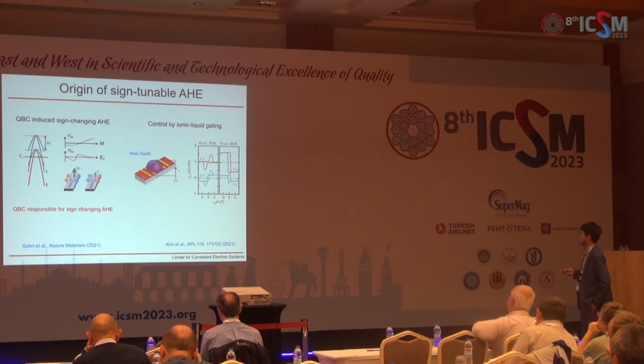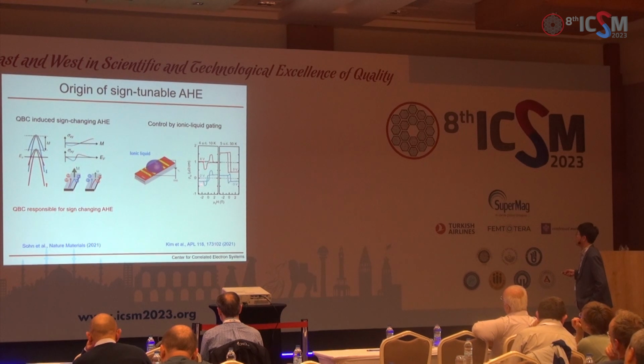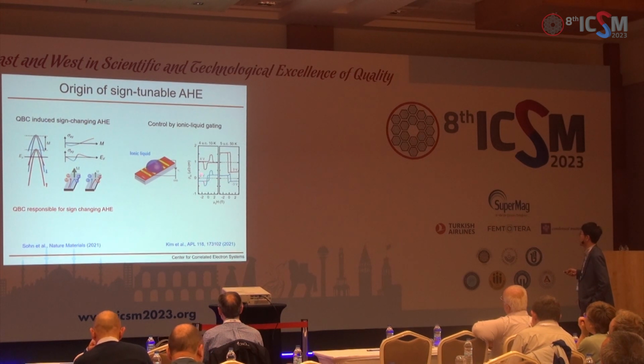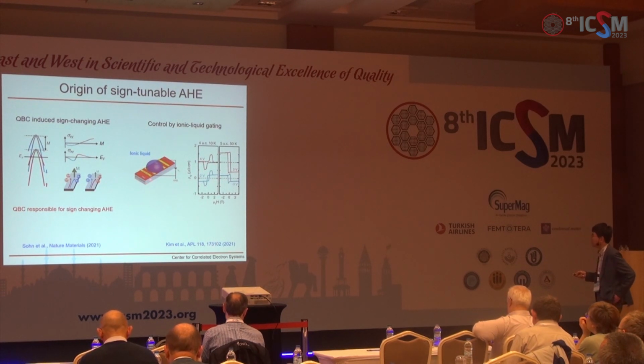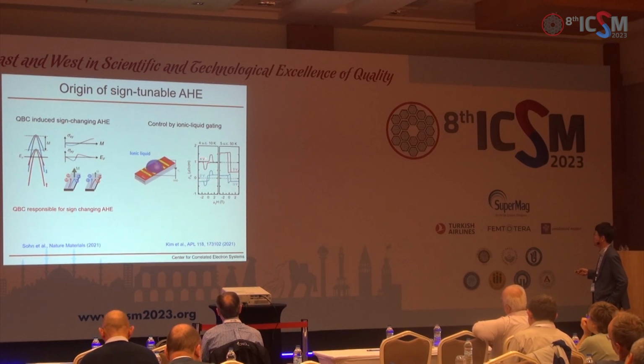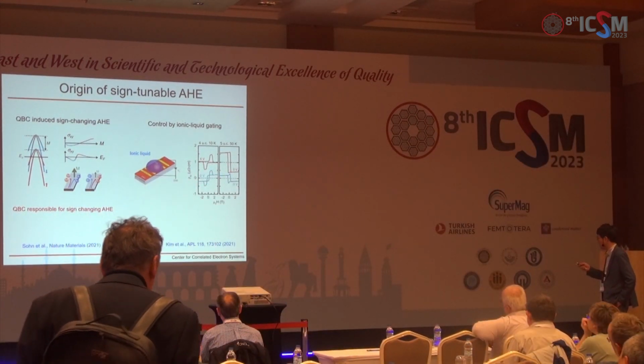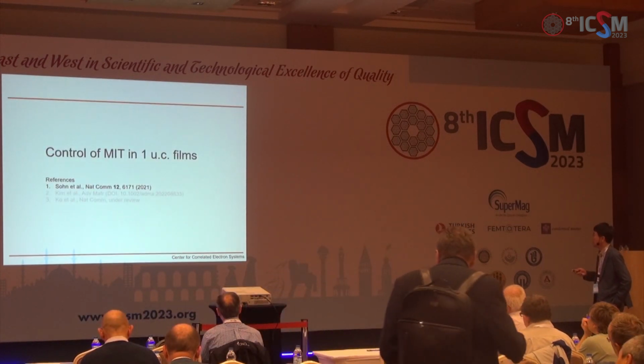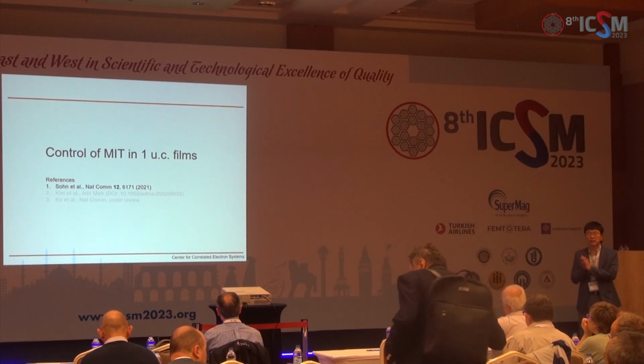Using ionic gating on this 4-unit-cell strontium ruthenate, as we change the gating voltage, we can change the anomalous Hall effect. In this case, you can tune it from negative all the way down to 0. We need a higher voltage to convert it to a positive sign, so we couldn't get there. But anyway, we were able to control the anomalous Hall effect. So that was a 4-unit-cell film.